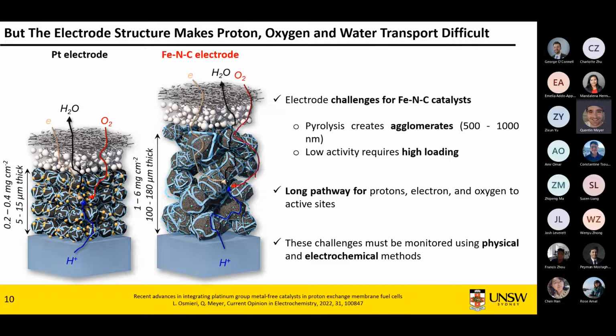are, if you look at PGM-free catalysts, firstly, often the synthesis is done through pyrolysis. Pyrolysis is going to right away create large particle agglomerates that are going to stick together no matter how well you try to separate them afterwards. Another issue is that the materials are not quite as active as platinum. Because they're not as active, you need a higher loading. What you typically have is a thickness between 100 and 180 microns, and 1 to 6 milligrams per square centimeter. 100 microns is the thickness of a human hair, so it's something you can actually see with your own eyes because it's so thick.